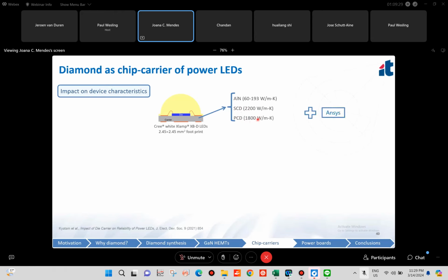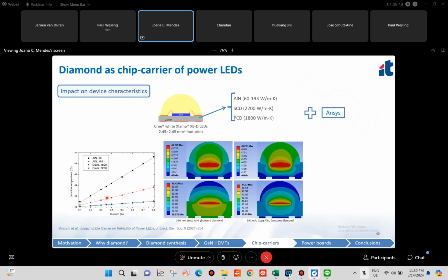And we used ANSYS to perform the multi-physics simulations. Of course, we had to make some assumptions. And we obtained these values for junction temperature as a function of the current. So the nominal current for these devices is 350 milliamps, so it will be here. And here you have the extreme results. So on the top, we can see the temperature distribution for the diamond carrier, single crystalline. And here at the bottom, you have the temperature distribution using the worst aluminum nitride carrier.